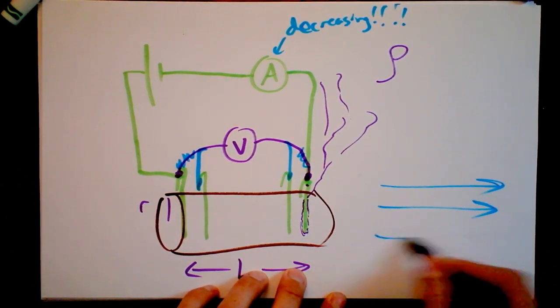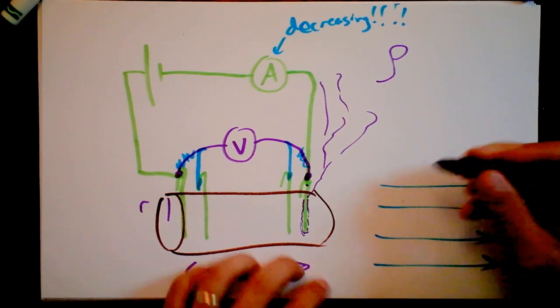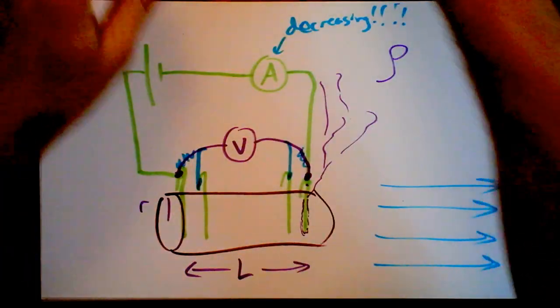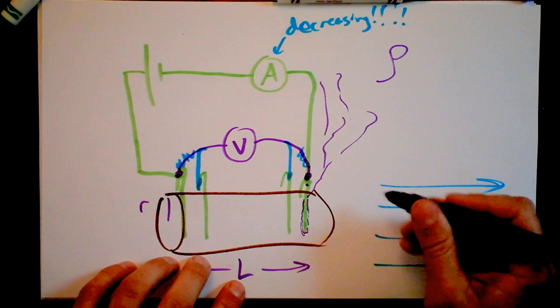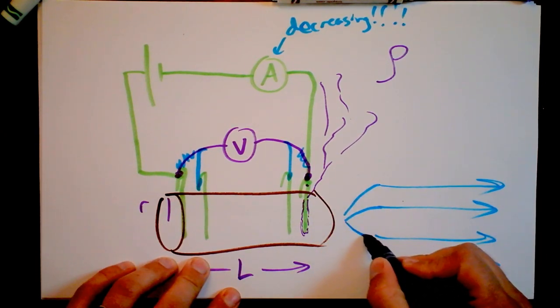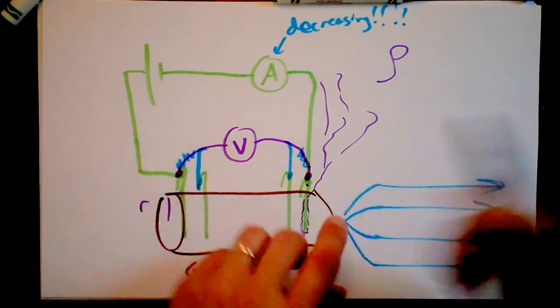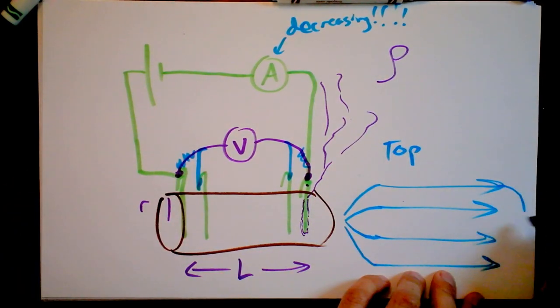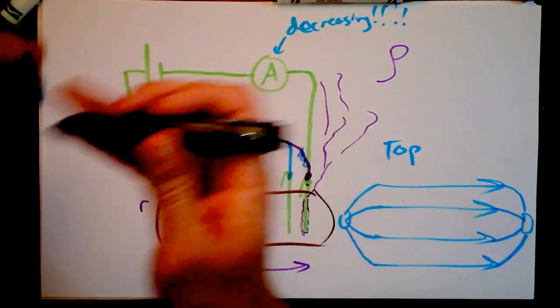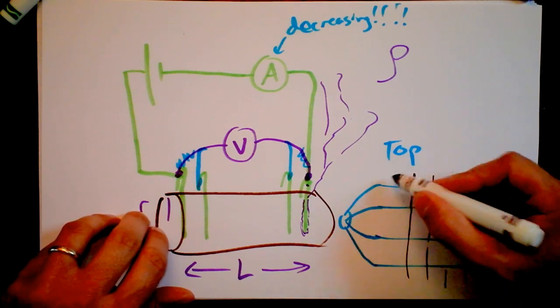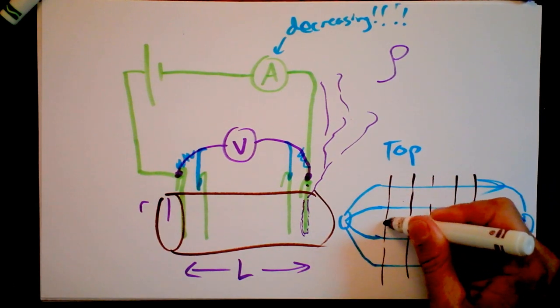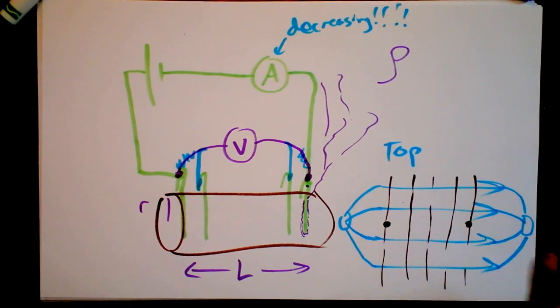So you get yourself an electric field in this case, be going this direction, right? You can measure that electric field by measuring the voltage of a certain equipotential and another equipotential. So that was my discussion about how to put them in a little bit. We do know that if you're viewing this from the top that those field lines will be coming out from that probe. And this is a top view. And then they're going to be coming back down into the other paperclip probe. But you can look at those equipotentials and in the middle, we're going to be happy to say that the equipotentials are equally spaced and parallel. And so that's nice. So you could put a probe right here and a probe right here and you could actually get at the value of the resistance of the material.